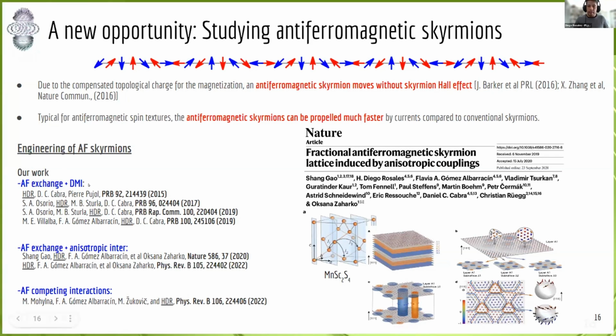I have worked a lot on this kind of topic in two-dimensional materials, where the Dzyaloshinskii-Moriya interaction is responsible for inducing this texture, or in three-dimensional symmetric materials, where a different kind of anisotropic interaction induces the skyrmion lattice, okay? And the last one is by the competition between antiferromagnetic couplings, okay?